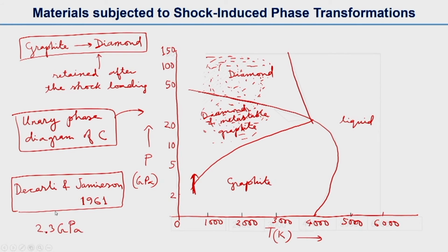This phase transformation results in very small grains, and also small particles which are polycrystalline. That means the particles are small size, and even one grain has a small size due to the limited time available for growth.